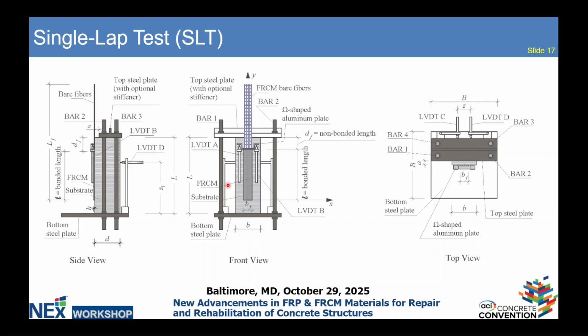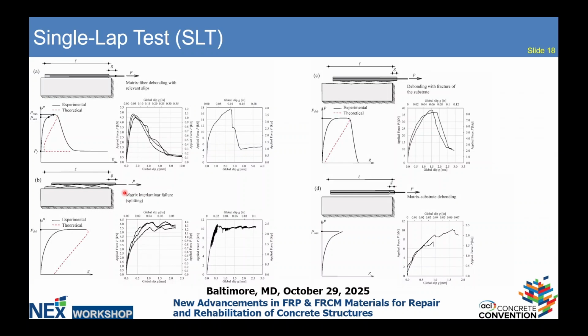There are LVDTs to measure the slippage of the fibers. There are optional LVDTs, which you see here in the back. You can measure the undesired rotation backward of the specimens, which will give you an eccentricity, so an additional peeling mode. So there are a lot of things that can be done to control your results. And then we provide in the guide a list of all the potential failures of all the composites that we tested over almost 20 years with FRCM and SRG.